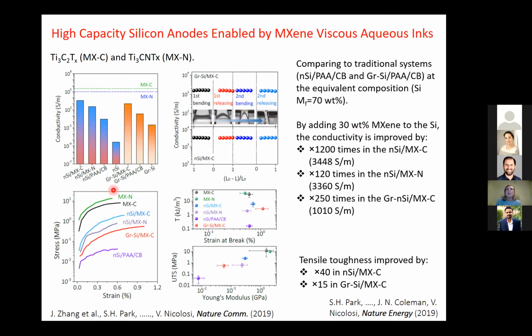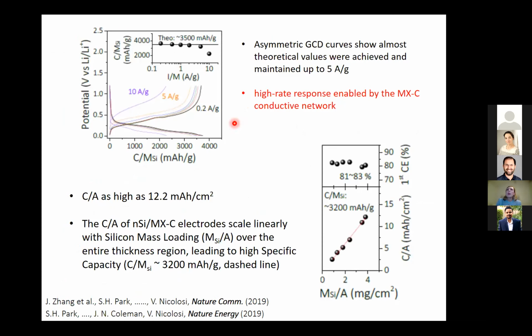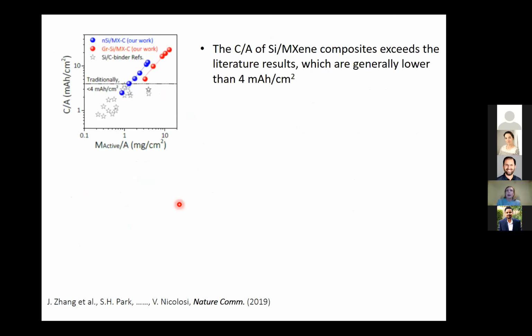And we also improved the mechanical performance of the electrode. So the tensile toughness was improved by about 15 to 40 times, again, depending on the type of silicon we were using. We could indeed achieve very, very high areal capacity. We achieved 12 milliamps hour per centimeter square. And this really opened up a lot of nice applications. And now we have patented this work, and Nokia Bell Labs is going ahead with this.